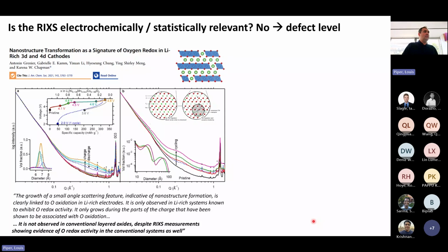Well, if it's forming trapped O2, the argument at the time was essentially that it forms little nanoscale voids, about 7 angstroms, where there would be an O2 molecule trapped in your structure. The idea is you can use scattering to observe things that are not there, because of the way in which the voids would scatter the X-rays.